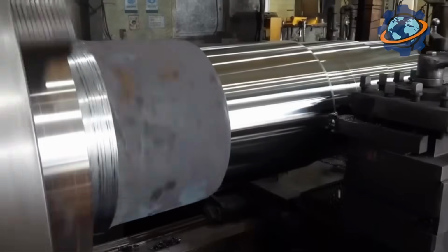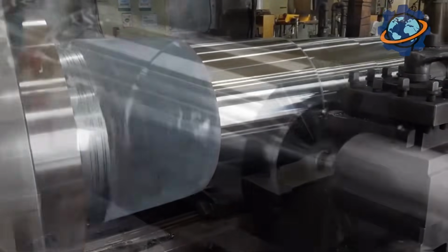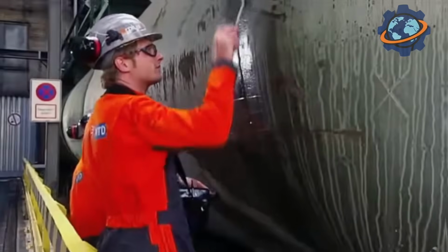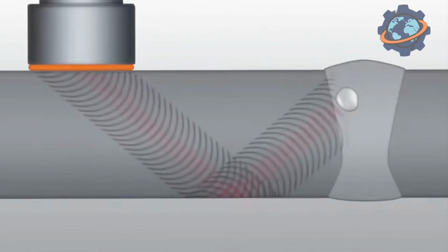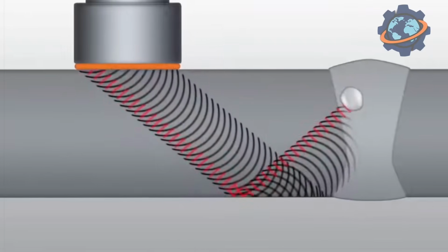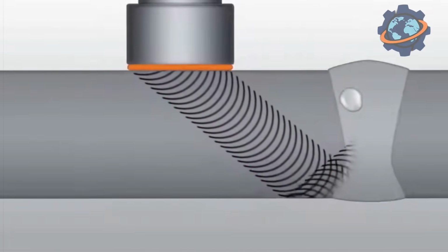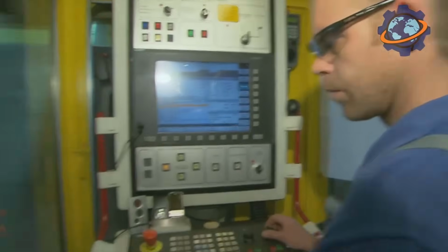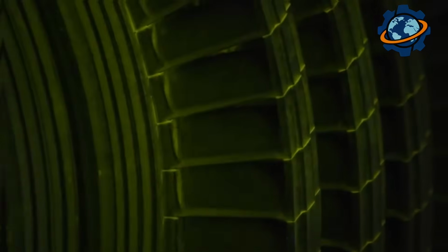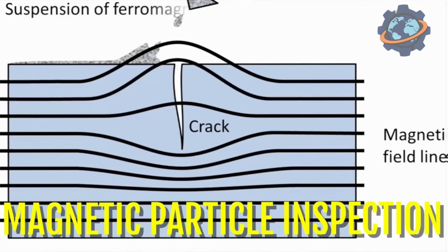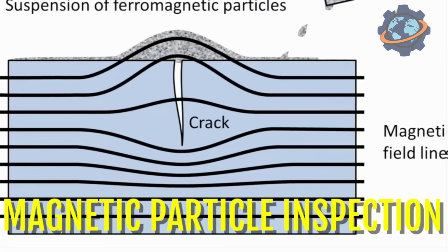The most critical moment is quality control. Each shaft undergoes ultrasonic defect testing. Special sensors send ultrasonic waves through the metal's thickness and listen for echoes. If there's a void or crack inside bigger than 1/8 of an inch, the sensor will find it. They also perform magnetic particle inspection of the surface, which can detect a crack less than 1/100th of an inch deep.